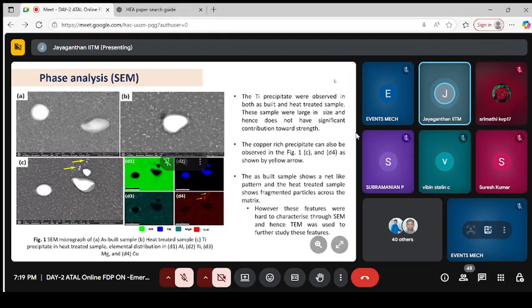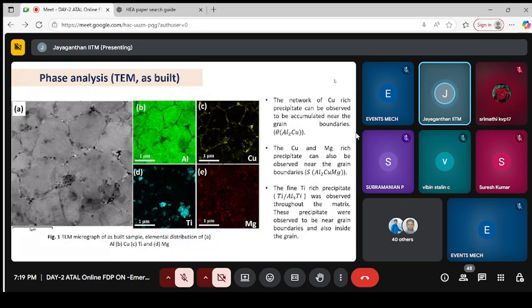And again, look at here through scanning electron microscopy. Whether we get any signature for the presence of titanium, SEM was not giving a detailed picture. And by doing TEM, we are able to identify. The transmission electron microscope is another technique wherein we can go much deeper in length scale. We can look at nanoscale pictures, even atomic length scale. If any precipitate phases are present, we can detect them through this transmission electron microscope.